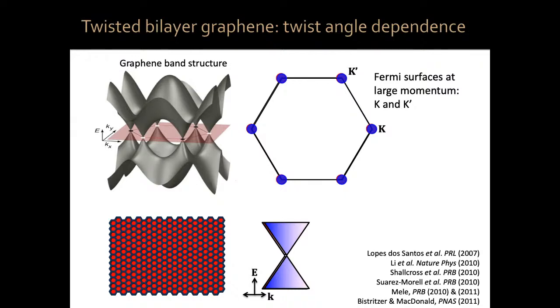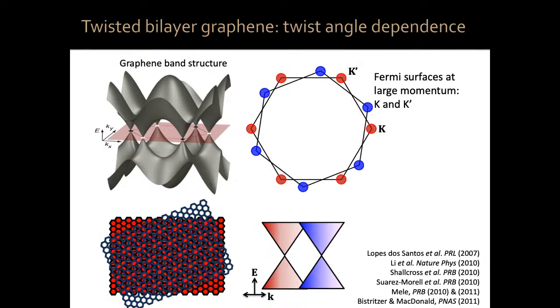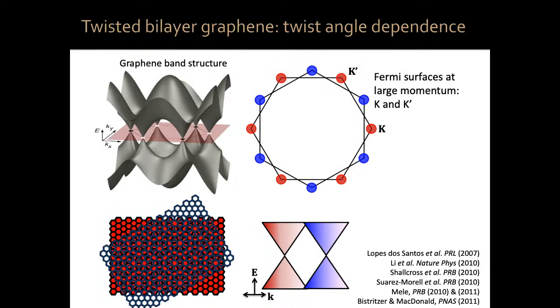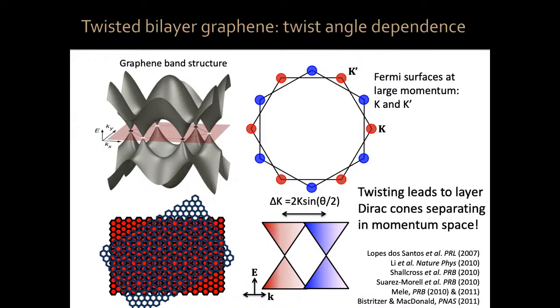And now, if I rotate the 2 lattices in real space, the reciprocal spaces also rotate. As a result, the Dirac cones from layer 1 of graphene and from layer 2 of graphene get separated in momentum space. So twisting leads to layer Dirac cones separated in momentum space. So let's do the following. Let's start from an angle which is already small, so that the separation in momentum space is proportional to the sine of the angle, so therefore the angle for small angles. And then let's see what happens.